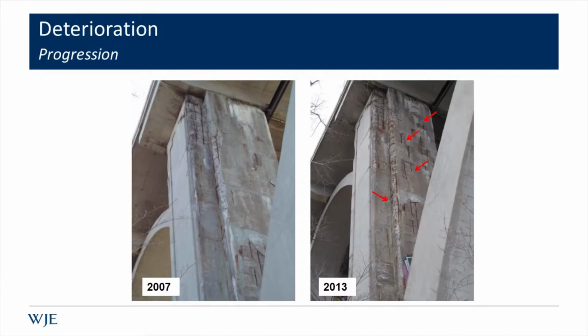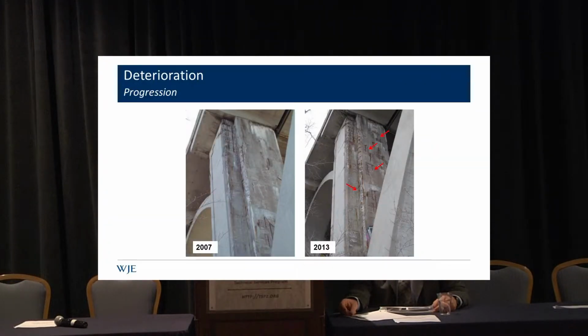And as Dan mentioned, our first investigation was for Hennepin County in 2007. The image on the left is one of the land piers and a photo we took at that time, where you can see some evidence of corrosion-related damage, chloride-induced corrosion, directly below one of the deck expansion joints. 6 years later, when we were out updating repair quantities and getting another look at the bridge, you can see visually the extent of the deterioration and the progression. And this should be somewhat intuitive that deterioration isn't a static thing. It's not going to happen and then stay the same. Chances are it's going to keep progressing, if not accelerating. And this is just one example of one element on the bridge where that was certainly the case. And that's just 6 years' time.